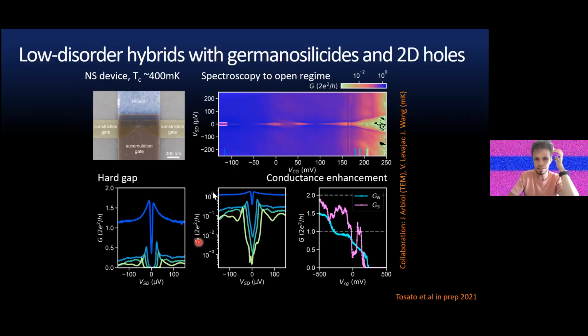And here you see a 2D plot where you can tune, basically transferring this device, in this NS device, from really a closed spectroscopy regime to a really open regime. And in spectroscopy, we really see reduction of the subgap states by at least two orders of magnitude, which in the literature suggests a hard gap. And we also see enhancement of conductance in the open regime.